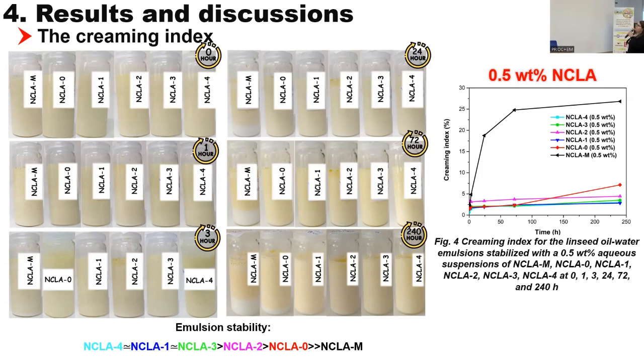The poorest results were obtained for the emulsion stabilized with the control sample, the one obtained only with hydrochloric acid, and for NCLA0, which were the fibers obtained only in the presence of lactic acid. We also see from figure 4 that the creaming index is in fact an indicator of the stability of the emulsions, being directly proportional with the instability of the emulsions. And we can see the high difference between the emulsions stabilized with the fibers obtained by chemical treatment with lactic acid and the fibers obtained by chemical treatment with only hydrochloric acid.